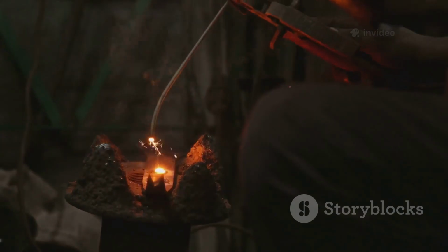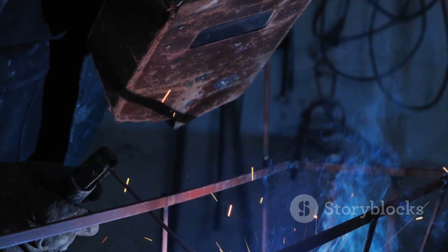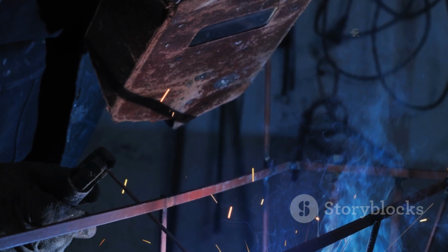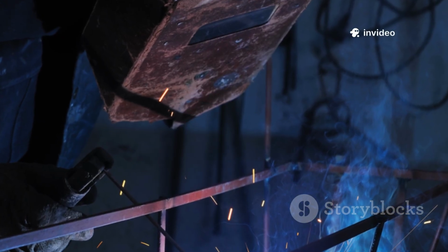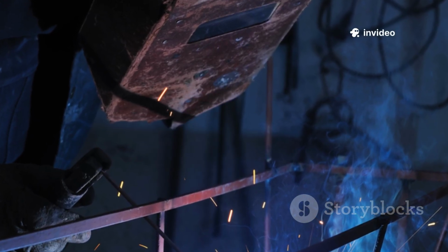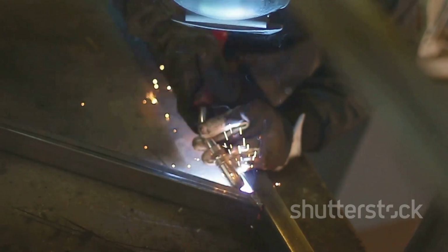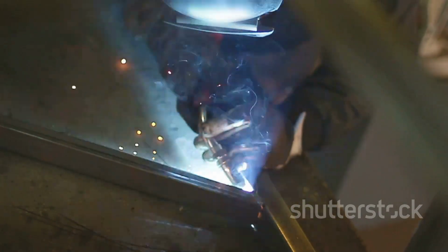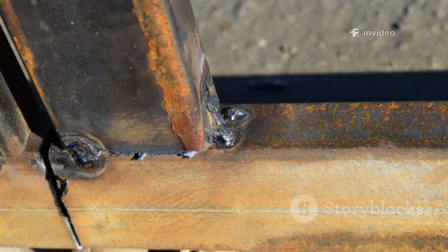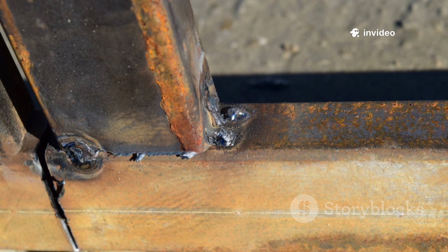One of the most critical aspects of this whole process is shielding the molten weld puddle from the atmosphere. Air is made up of about 78% nitrogen and 21% oxygen, and both of these are highly reactive with molten metal. If oxygen gets into the weld puddle, it causes porosity. Those are tiny gas bubbles trapped in the weld, and it makes the weld weak and brittle. Nitrogen can also cause brittleness and cracking.